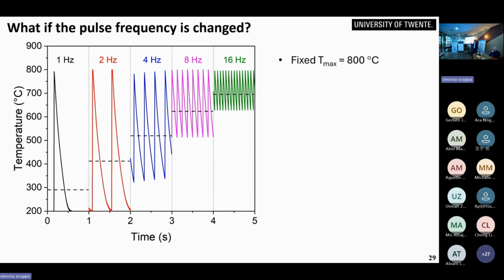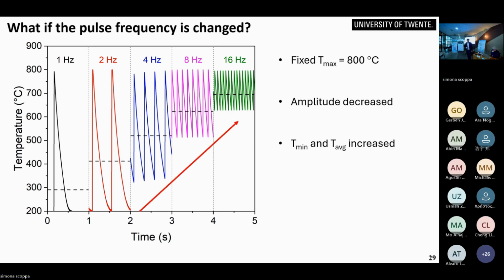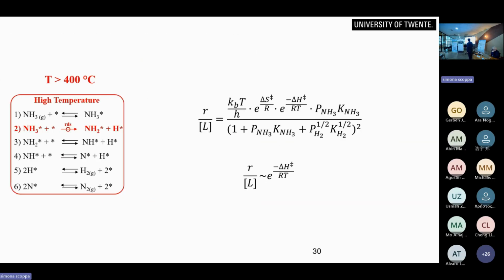A fundamental question, of course, is how this can respond to changes in the frequency and the temperature. Maybe I don't have time, by the way, to go through all of this. But one of the things we can do is vary the frequency at which we send the pulses. The consequence is that the average temperature goes up, because you don't have enough time to cool off the system before the next pulse comes in. We can then see the effect of the amplitude and the average temperature on our kinetics. In principle, you expect that the higher the temperature, the better the performance. That's the general rule.